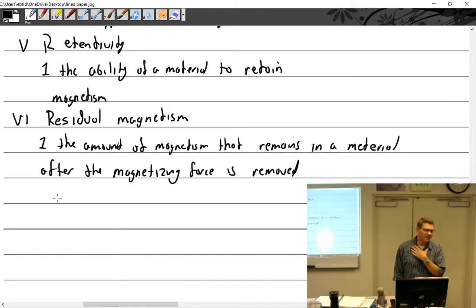So even if it has high retentivity, it's going to lose some of it. I don't know of any material that you can magnetize to a specific point and it just stays there. It's always going to fall off a little bit. Which is why I say that even on a part where you can get away with residual magnetism inspections, you're still better off and it's still more sensitive if you're using the continuous method. Material properties.